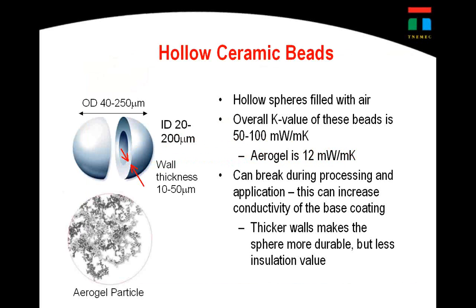Yes, there are other technologies out there. I just want to mention the ones that are probably the most prevalent. You're looking at a ceramic bead right here, and that's primarily where I showed you those tanks before, the three tanks, so the ceramic versus the aerogel particle treatments. The difference between these is that they're not that efficient. The K value of the beads is obviously a lot less than that of an aerogel. So you're looking at milliwatts per meter Kelvin at 50 to 100, whereas aerogel is at 12. This is where you get that efficiency.